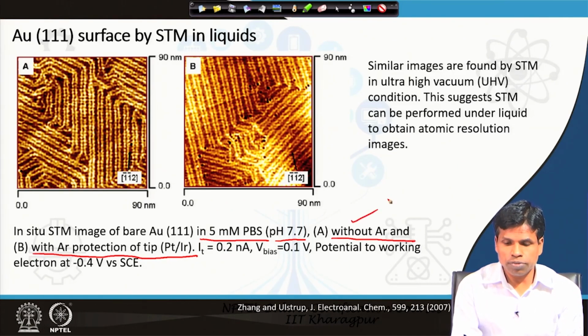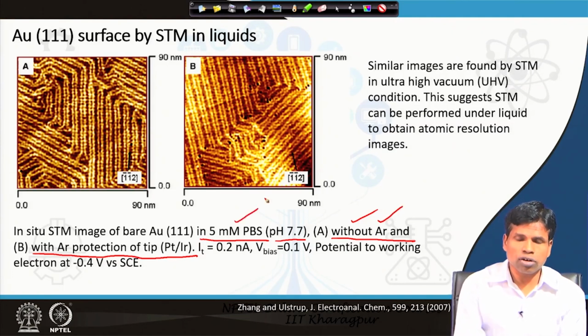The protection was done just to see what the difference is, but actually what is observed is that there is no difference at all whether it is done in an inert atmosphere or without an inert atmosphere. So, without argon means in the presence of oxygen, because it was an aqueous electrolyte solution.